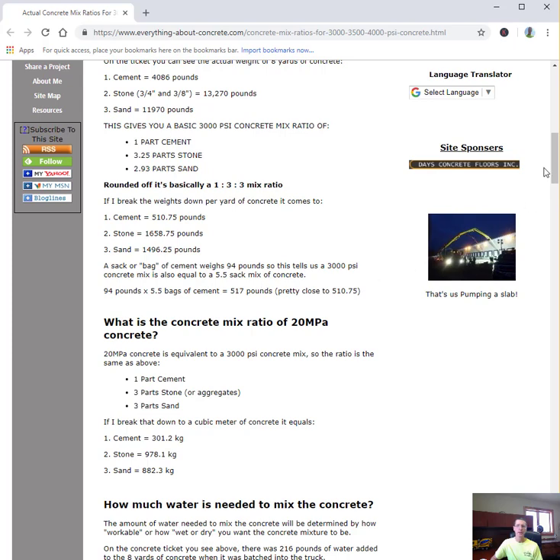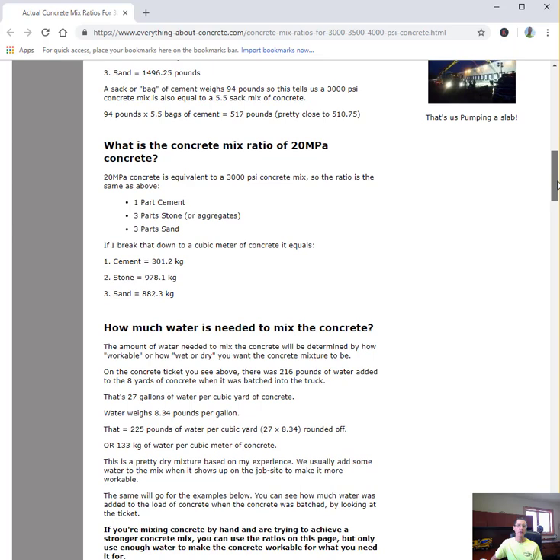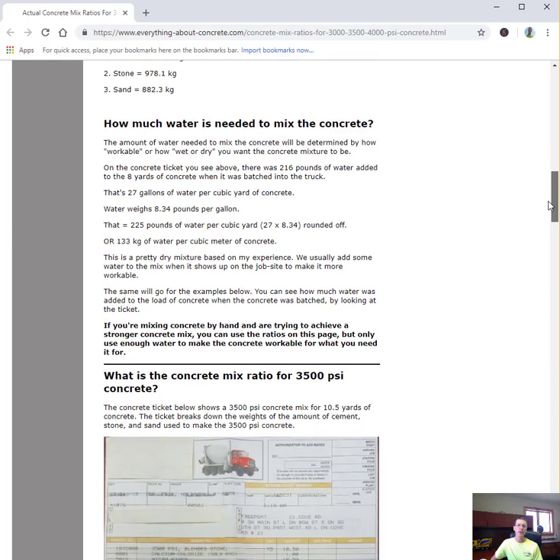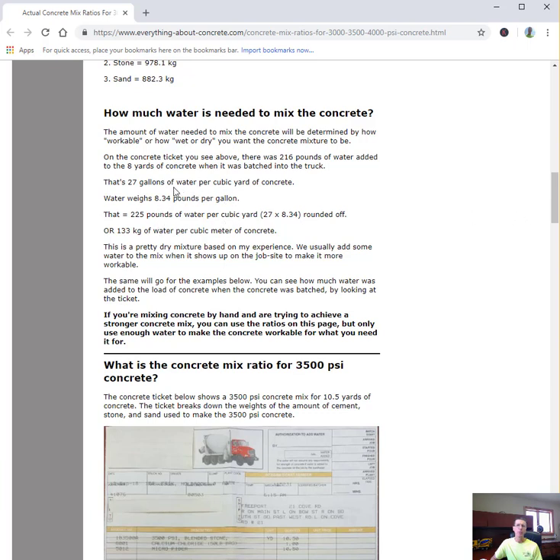How much water do you need to mix that concrete? The water is going to vary depending on how stiff or how wet you want your concrete to be. Generally we pour around a 5 inch slump to a 6 inch slump, which is the term used to measure the flowability of the concrete. These numbers are probably for more like a 4 inch slump, which is something a little stiffer. They used about 27 gallons of water per cubic yard to get about a 4 inch slump. So in that 8 yard load that was about 225 pounds of water.